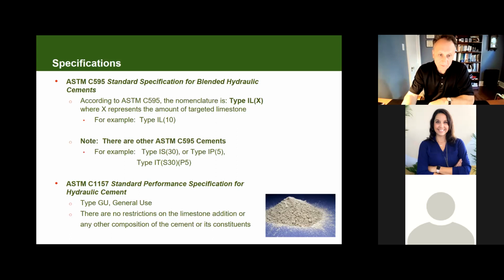Now, if you look at C595, you're going to see some other cements in there. For example, you'll see a Type IS(30). What is that? Well, that'd be a type 1 that has 30% slag cement blended into that 1 ton of cement. There's a type IP(5). What's that? Well, that would be a type 1 that has up to 5%. It might be like silica fume blended into that 1 ton of cement. And then you can blend several cementitious materials. You can have a IT(S30)(P5), and that would be 30% slag and maybe 5% silica fume, all blended into that 1 ton of cement.